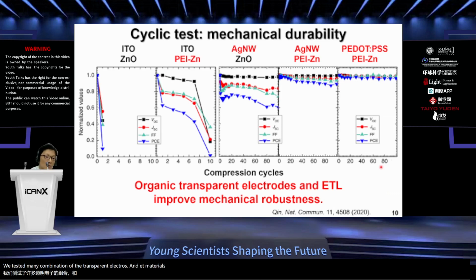We tested many combinations of transparent electrodes and ETL materials. When we use ITO, a very brittle transparent electrode, and apply harsh mechanical strain to the devices, the device performance was sharply degraded even after only one cycle with the ITO and zinc oxide combination. But such harsh degradation was suppressed dramatically when we replaced the zinc oxide with PEI-Zn, as shown here. With this combination, the device can work after around 10 cycles.